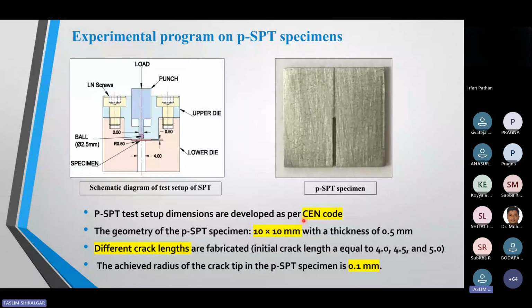Here, I would like to give some experimental program information on the PSPT specimens. Here, I have manufactured this type of specimens. You can see these dimensions. I took these dimensions from this CEN code. On the right side, you can see the fabricated specimens, 10 mm length, 10 mm width and 0.5 mm thickness. This geometry I took from the CEN code. The CEN code is famous in the European countries. They are using this code to make this experimental program for the specimens.